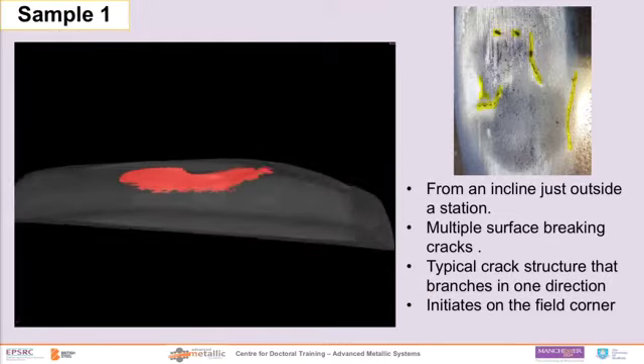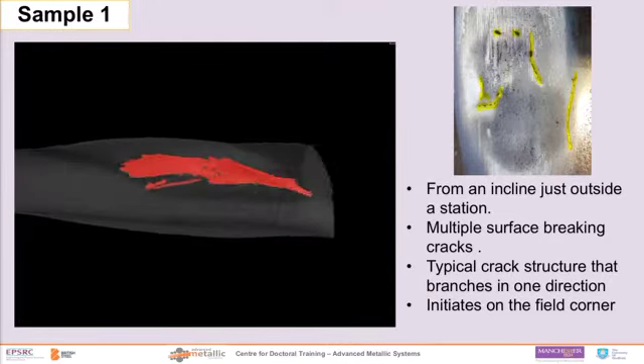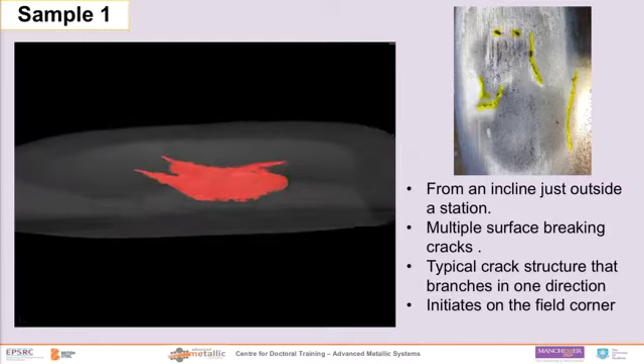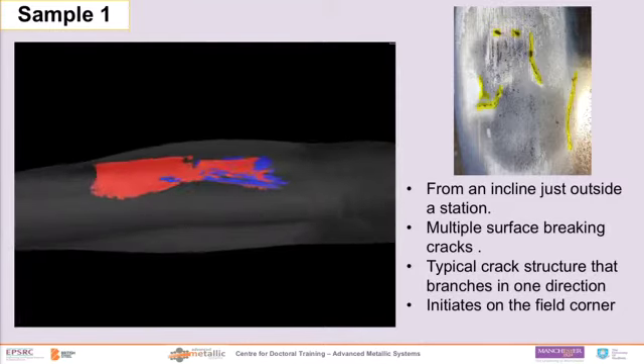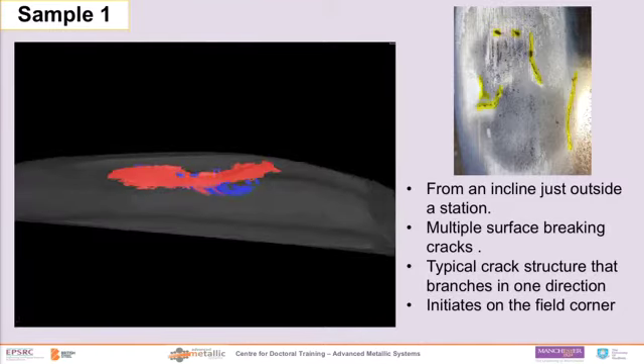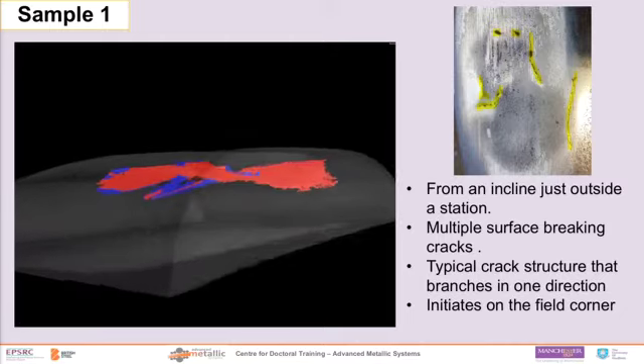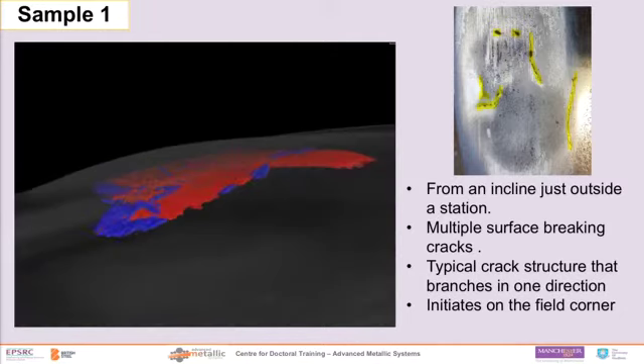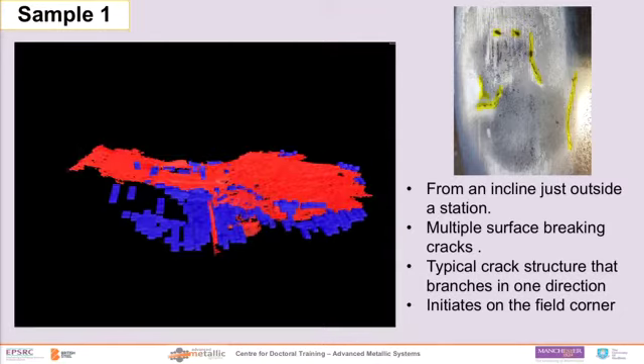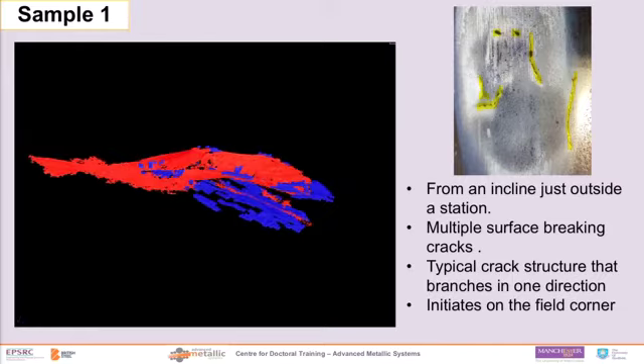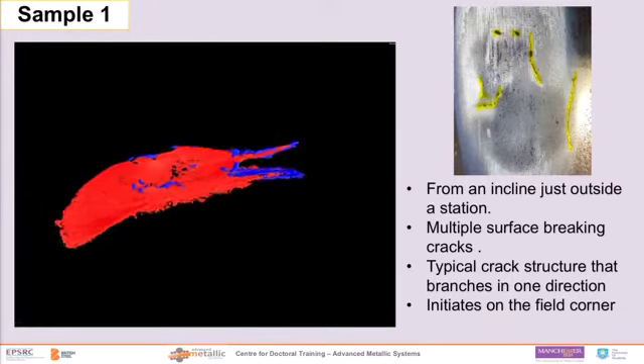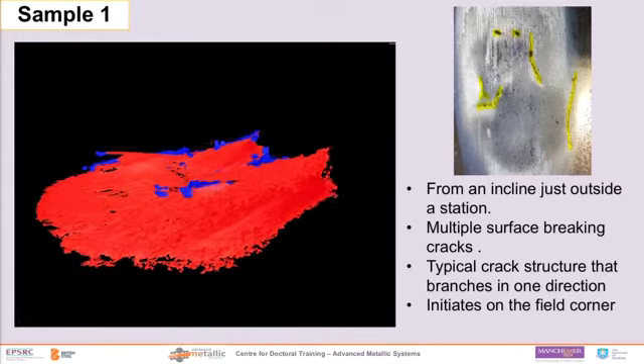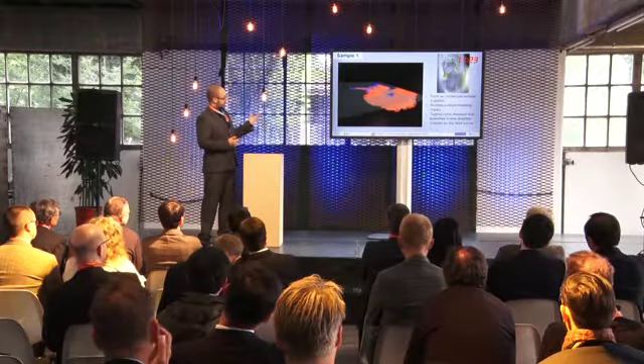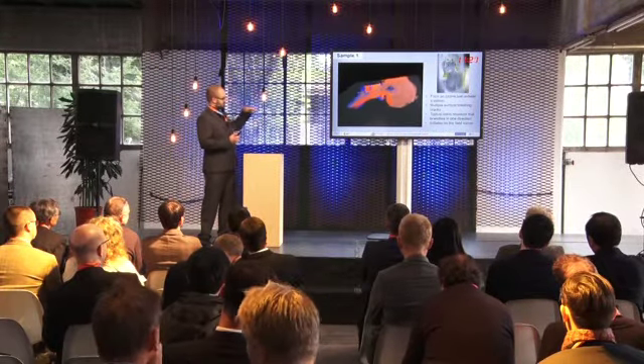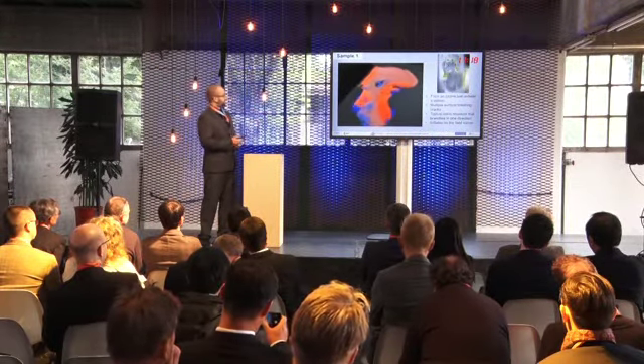So this is a model of one of the samples. The red represents what the automatic crack detection software was able to see. The blue is then what I had to manually go through and add in myself, because due to noise, etc., the software can't see everything. So as you can see, you've got your main crack at the top, and then you do have a crack below that, but it isn't traveling deep, it's just traveling just underneath the other one. And in a moment, some green will turn up.